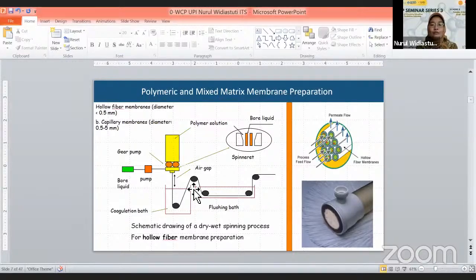And this is how to prepare the hollow fiber membranes or capillary membranes using the polymer solution, as I mentioned before. The polymer solution goes through the spinneret at a certain size that we can set based on the diameter of the membrane. After that, the membranes come to the coagulation bath and then the flushing bath, and we can roll the hollow fiber membranes after that.